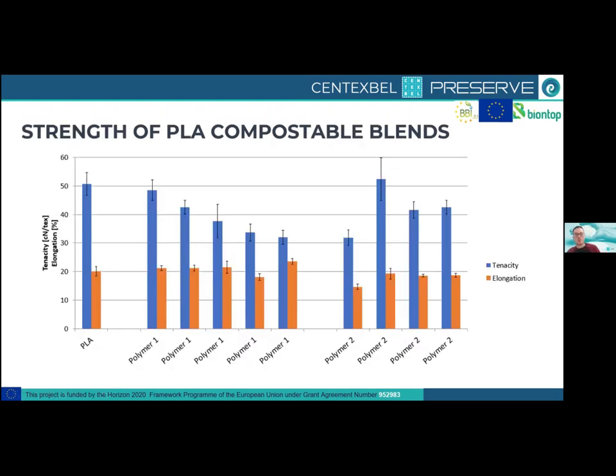And also what I want to show is the strength of the material, because when we work with PLA blends, PLA is a very good, very strong material, but when we blend it with different other polymers, they actually have less strength. So this is also influencing the total strength of this material. On the left, you can see the reference of the PLA. You can see a tenacity of around 50 centinewton per tex with an elongation of around 20%.